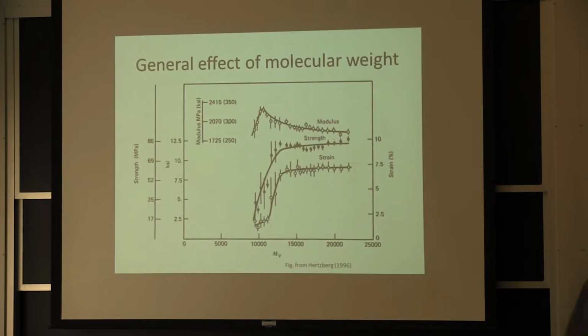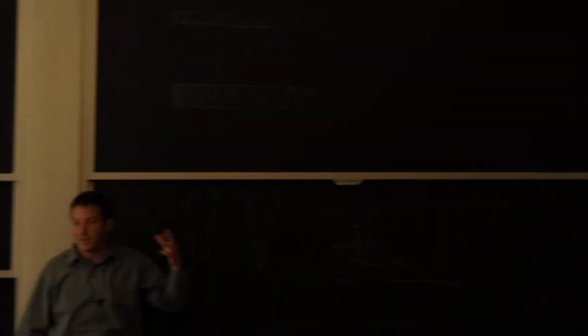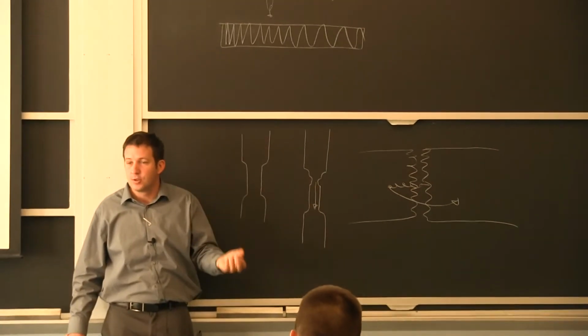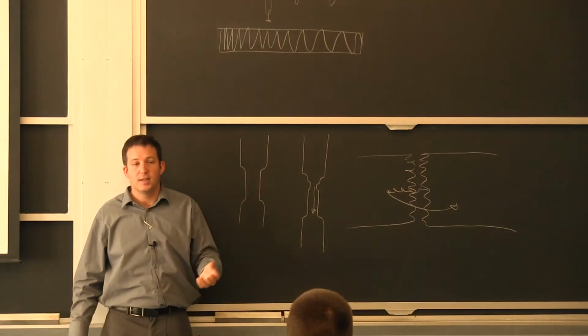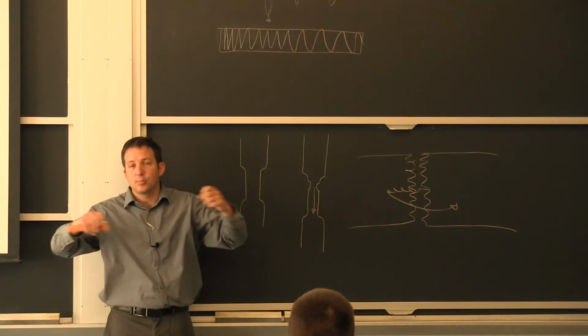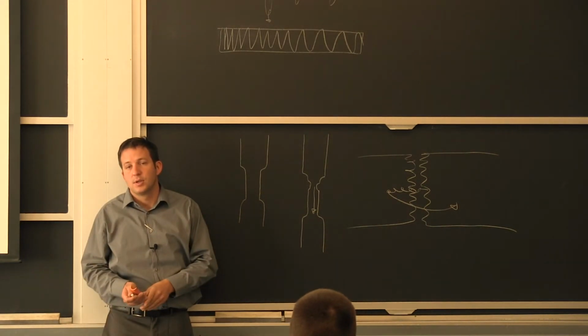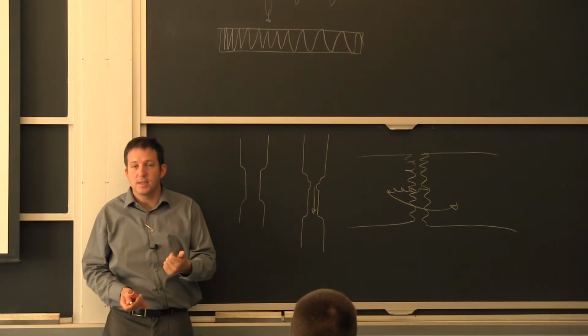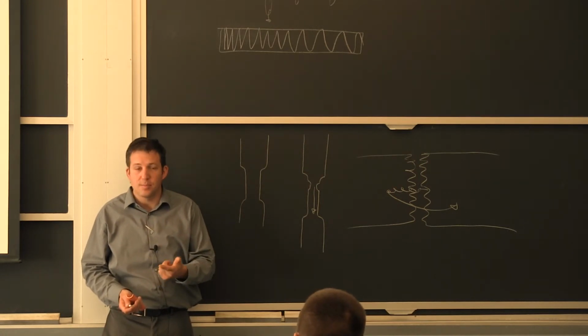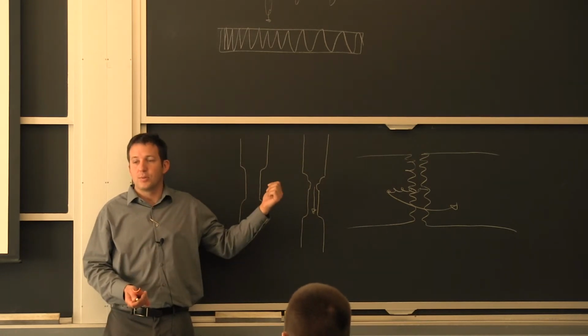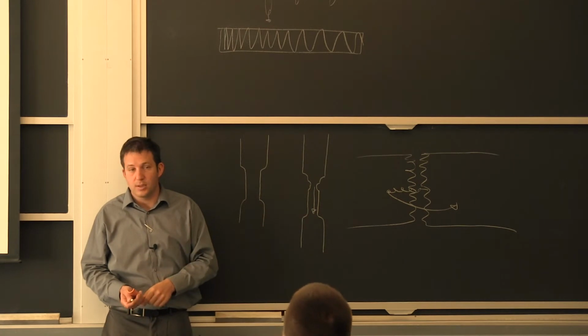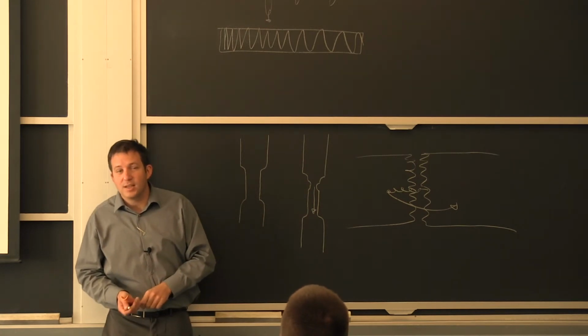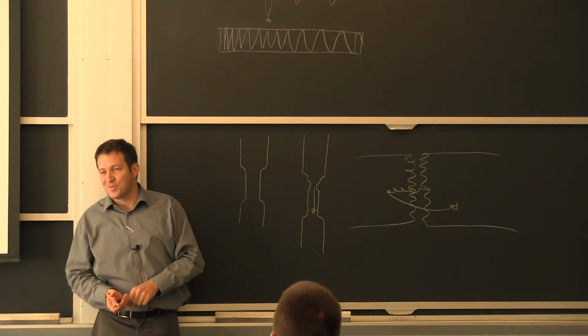So there's much less effect of molecular weight in a tensile test where I reach 300–400% strain than when I'm trying to really separate the two components. So that's what happened in crazing in notches. So the impact energy for polymer will depend on molecular weight a lot. The downside is molecular weight is hard to measure.